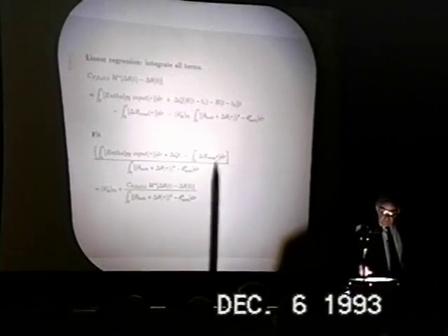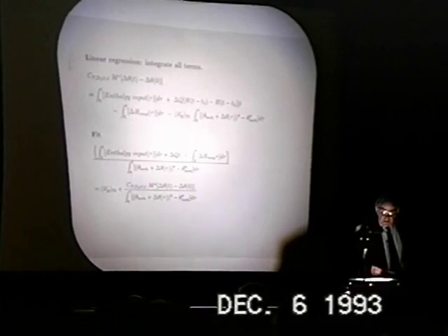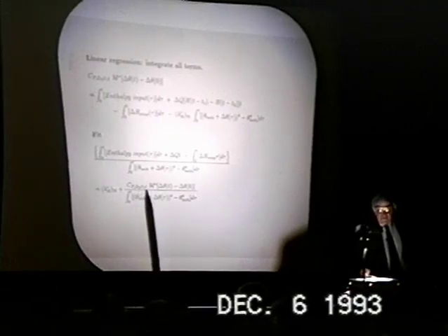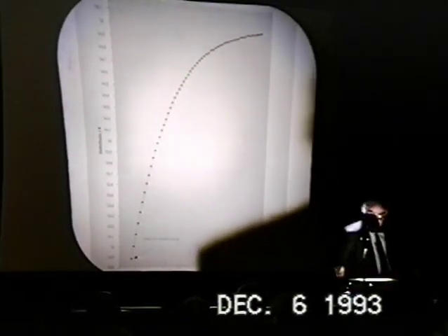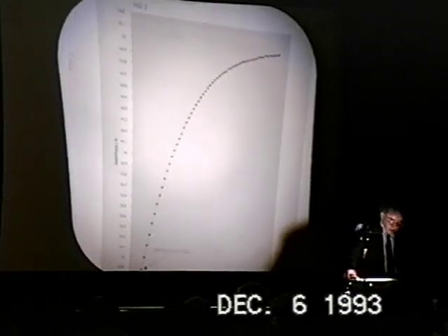You can integrate all the terms individually, and then you can fit the integrated terms to a linear equation. And here you have the enthalpy input, the calibration pulse, the evaporative heat term, divided by this temperature function. On the right-hand side, you have again the temperature function, and you have the water equivalent of the calorimeter. And this is a straightforward y equals mx plus c type equation. It's a linear equation, and it is perfectly adequate to do the analysis. And you don't need to run your calibration pulse forever. You can just take a suitable section of the data set, and you can say, do I get a linear regression? And indeed you do.